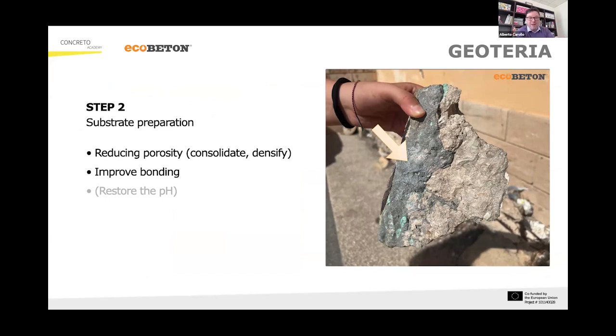it's not a matter of having good products, it is a matter of having a good system, because very often we observe that after a reparation, the reparation after some years detaches from the original concrete, and it is not detaching at the interface. It is detaching below the interface. So some part of the original material is pulling off, you know. Why? Because of poor substrate preparation. You have to reduce porosity, you have to improve the bonding. Usually you have to restore the pH, realkalinization. We don't need that with geopolymers, but this is a good suggestion for concrete reparation. So we choose a deep penetrating mineral sealer for doing that.